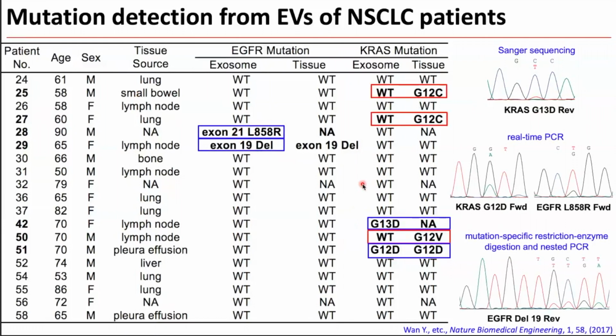However, there are 3 cases in which there are mutations from the tissue sample, but we were not able to detect them from the EV samples. So at this point, we realized the mutant allele fraction within these samples derived from plasma can be relatively low. So we actually need to use a more sensitive detection mechanism.